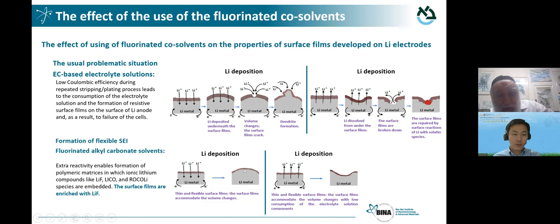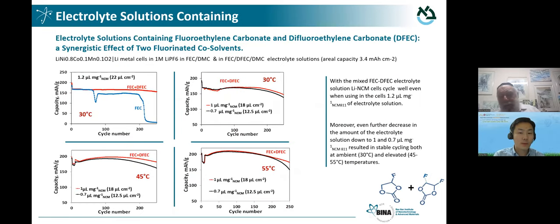In our case, thanks to unique surface chemistry, we can obtain flexible surface films because we obtain polymeric species together with ionic lithium compounds. So we have an ideal combination of species which are flexible, they form flexible matrices that can accommodate the morphological changes, yet behave like SEI, solid electrolyte interface. And this is thanks to a unique surface film.